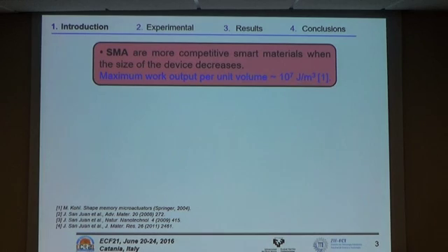So, as we all know, shape memory alloys experience this martensitic transformation, which provides the superelastic effect and the shape memory effect, and this is why they were quite used in many applications. And as smart materials, they become very attractive when you decrease the size of the device you want to use, because of one main reason, which is the maximum work output you can get per unit volume among different smart materials, which is about 10 to the 7 joules per cubic meter.